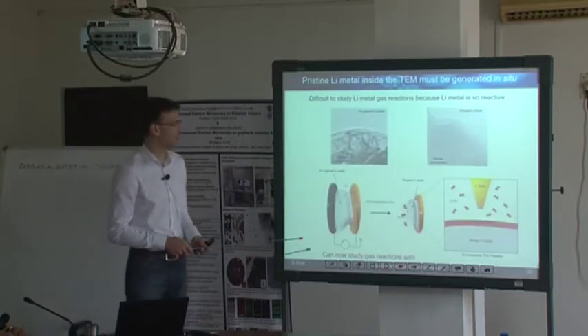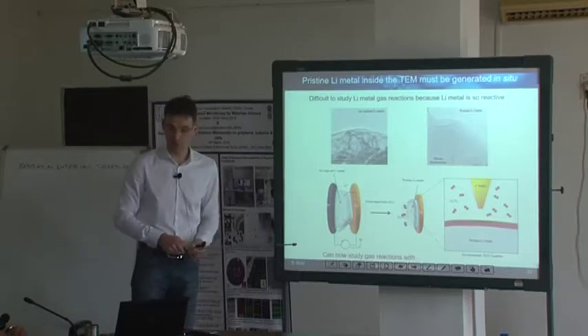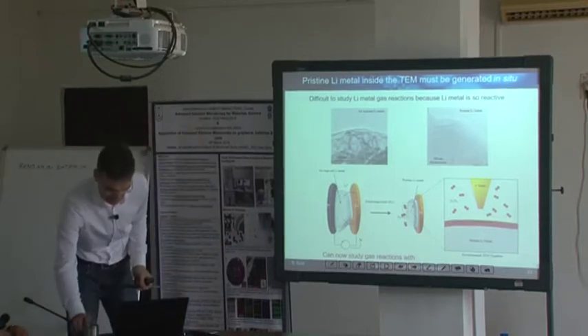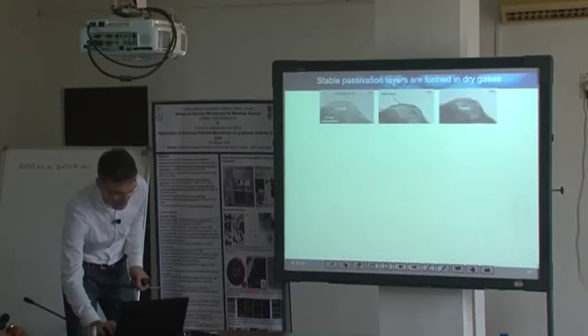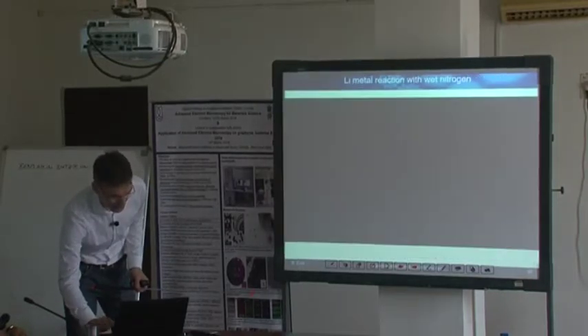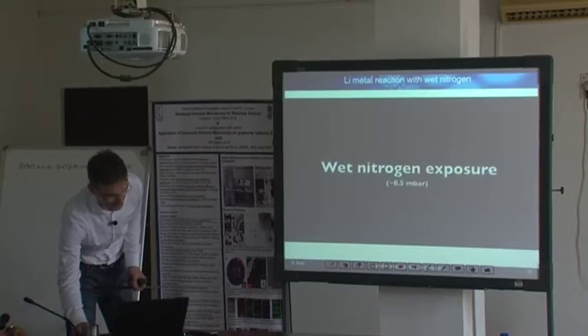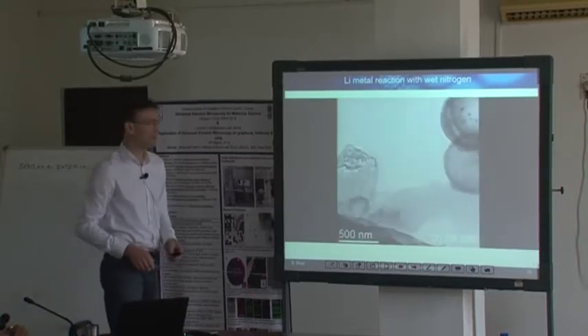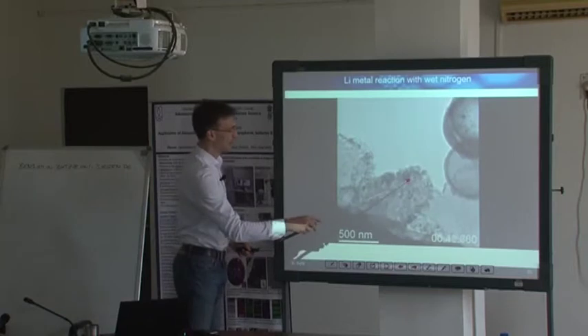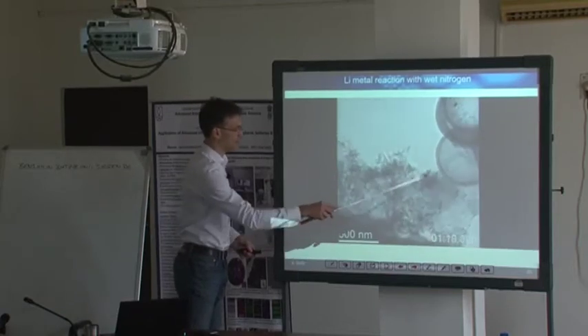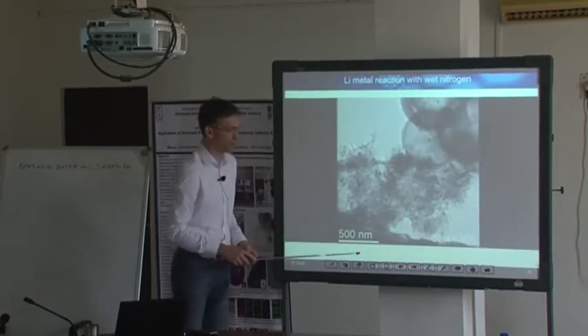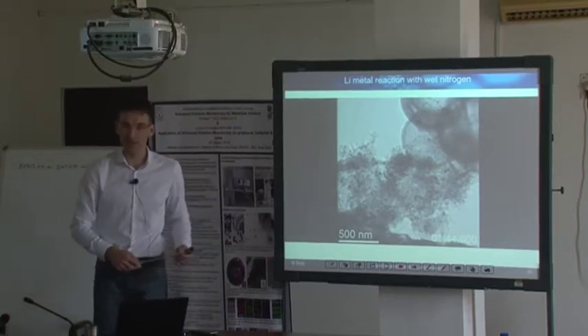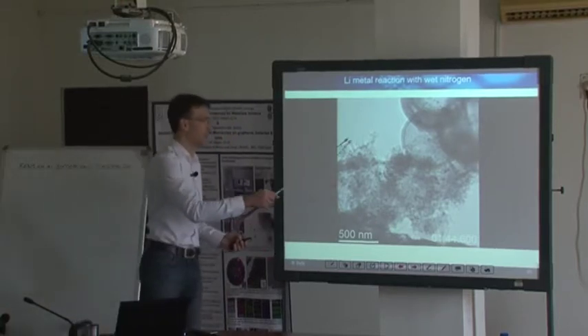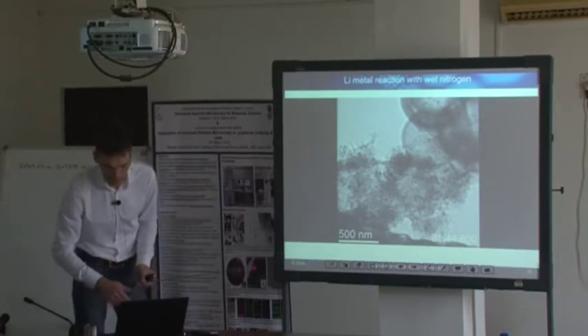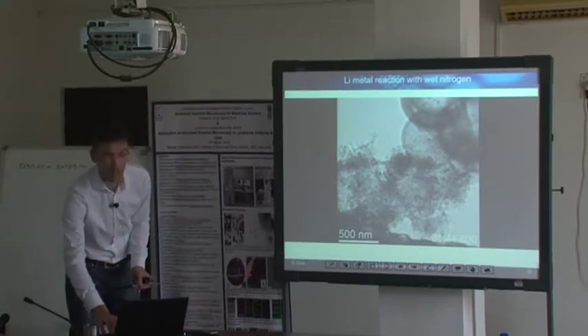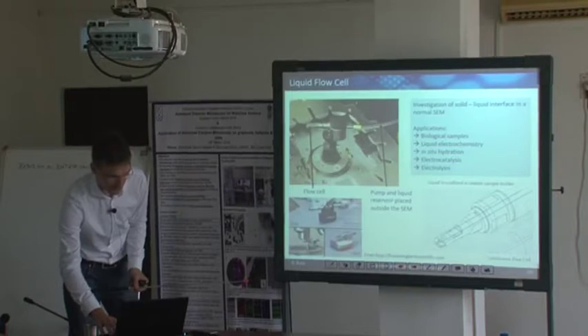This is the study on the corrosion of lithium, and I will not explain that in much detail. I would just like to share a second time this corrosion of lithium in wet environment. This is our metallic lithium here, and this is the corrosion layer, which is highly open porous. By such studies, we were able to understand the reactions going on and causing this drastic degradation of batteries.